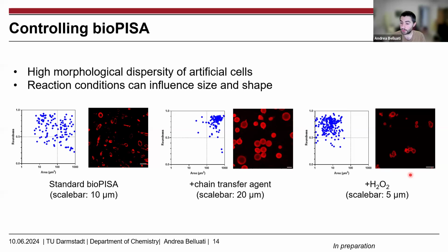We tried to use glucose oxidase as a way to remove oxygen and allow us to work with an open vessel. However, this hydrogen peroxide produced does react with the growing polymer chains, and so we do get a mixed control radical polymerization, that is ATRP, and free radical polymerization coming from the hydrogen peroxide.